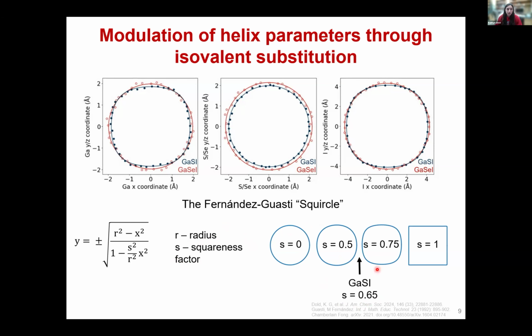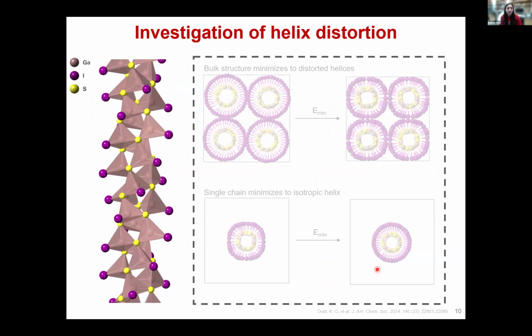To investigate the origins of this distortion, I then did a bond angle analysis as well as some density functional theory calculations. The bond angle analysis told us why these materials are so much more modular than the other known classes of all inorganic helices. This is because these metal-chalcogen-metal angles from these corner sharing tetrahedral building units are extremely able to handle the strain of various elements, because they can move around and the angles are much more flexible. From selenium to sulfur, we see an expansion of these bond angles, and this incorporates the strain that's induced by this smaller sulfur element.